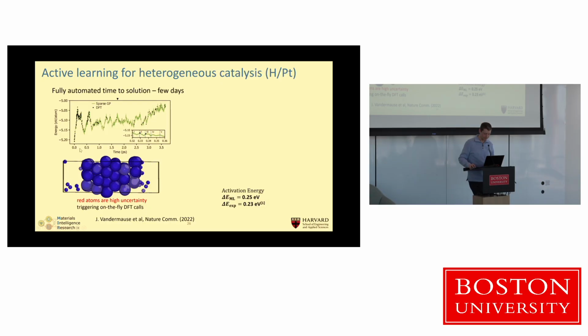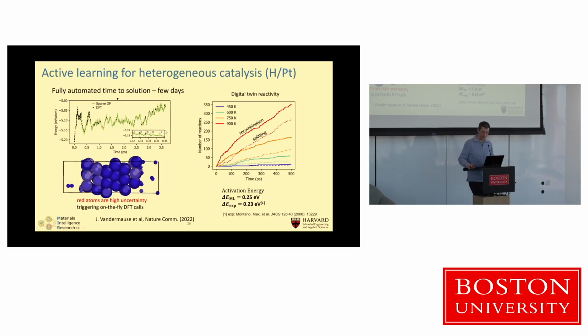And so this is an example of hydrogen reacting with platinum catalyst. And this model was essentially started with no knowledge. The Gaussian process model here has zero knowledge to begin with, so that's why you see in the beginning it does a lot of these requests to call DFT, so it automatically calls a quantum mechanical calculation, gets training data, and then proceeds afterwards. And then once it's done, you can actually test how good it is and compare to experiment. For instance, you can measure the activation energy because you can now run larger reactions and measure how many molecules reacted as a function of time, and then change the temperature of the simulation and compare to what experiments do exactly the same way as they measure reactivity as a function of temperature to get your activation energy.